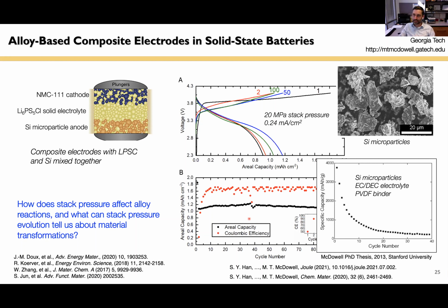So what I want to tell you about now is some of the more detailed chemomechanical investigations we've done to understand specifically how stack pressure is related to the transformations in these sorts of batteries with alloy electrodes. So stack pressure isn't something that I've talked about in detail yet. It turns out to be extremely important for solid state batteries. A number of these papers cited down here have done some really nice work on both understanding the effects of stack pressure on lithium and also understanding how stack pressure changes when you cycle. So we were inspired by this work to carry out some investigations of monitoring stack pressure, applying it and then monitoring how it changes due to the reaction processes in our electrode materials. And again, this is published in our Joule paper down here.